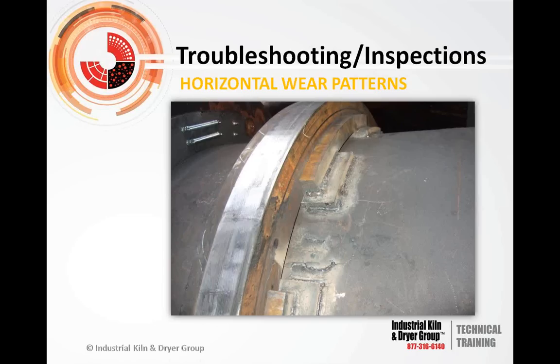Other types of flat spots that are wider in nature are typically a result of some kind of issue with the rollers. For example, a bearing failed, the roller seized up, and you wore a flat spot in the tire. Well, once you change out the roller and it starts rotating, that flat spot remained in the tire, transferred to the other rollers, and now you've got these flat spots that are transferring all the way around the unit.